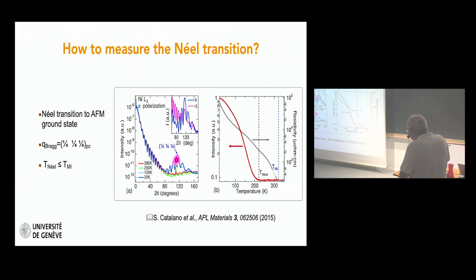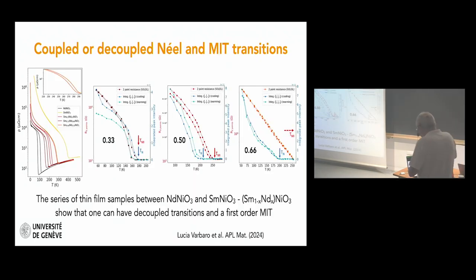You follow its intensity. This is intensity versus temperature, and you see, for instance, here, that this magnetic transition, this Néel transition, is around 200 Kelvin. So this is what we did with a series of samples with the goal of checking whether or not the metal insulator transition and the magnetic transitions are coupled. And the measurements are shown here.